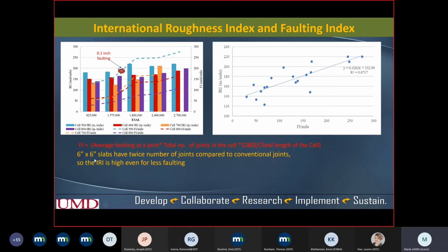What I would like to say here is that 6 feet slabs have twice the number of joints compared to the conventional joint. So if we drive on faulted joints of the small slab size compared to 12 feet by 12 feet, which is used in conventional pavement, the IRI can be high because of the greater number of joints, even with less faulting. The faulting value is 0.1 inch here, but the IRI actually exceeded the threshold value. We also developed a relation between the faulting index and IRI, and we saw there is a good correlation: more faulting, more IRI.